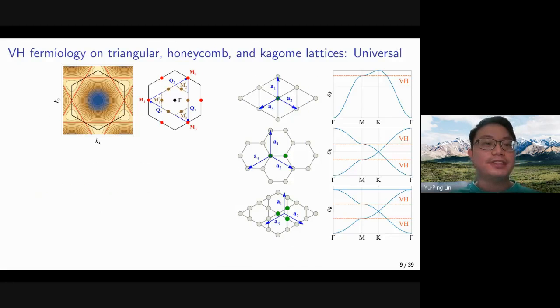So let me now look further into the Fermiology, that is the structural Fermi surface at the Van Hove singularity. It turns out that at the Van Hove singularity, the Fermiology is universal on the triangular, honeycomb and kagome lattices. So the three lattices will have this kind of band structures. We can see that for the triangular lattice, there is one Van Hove singularity, and for the honeycomb and kagome lattices, there are two.